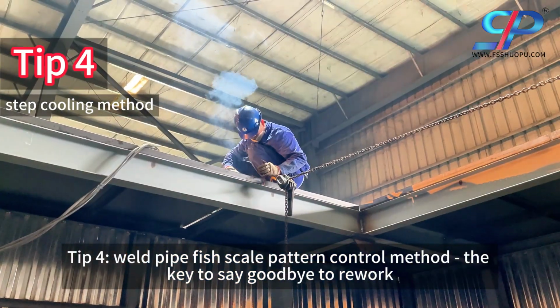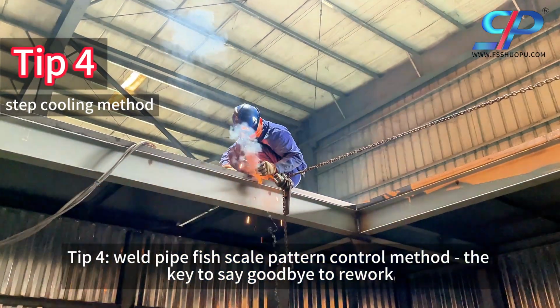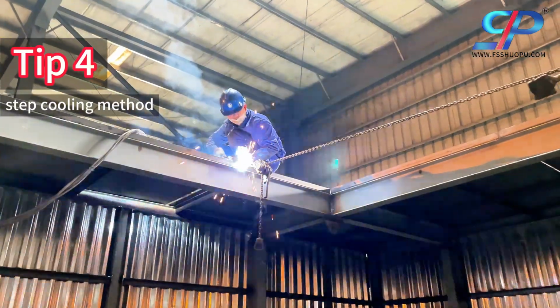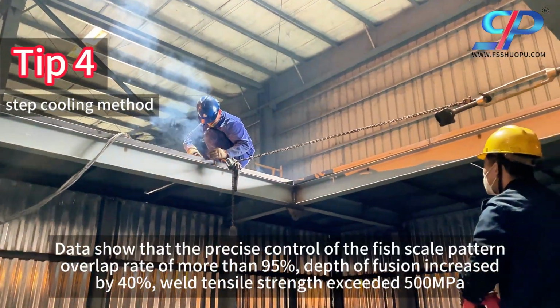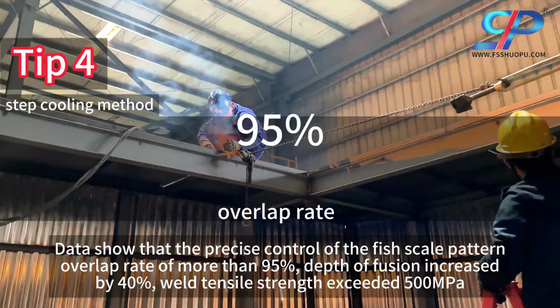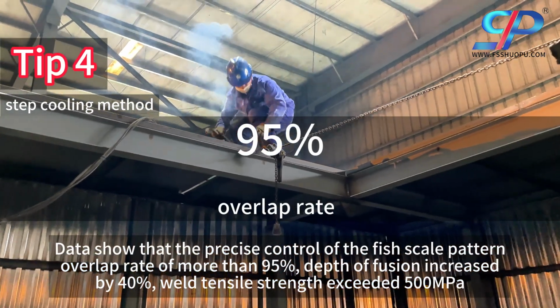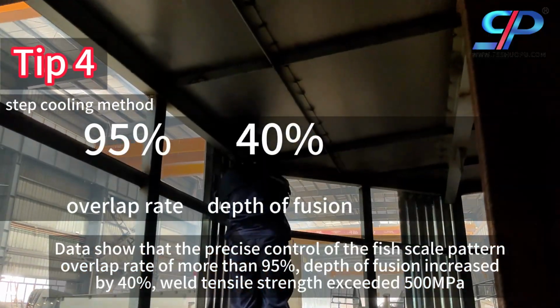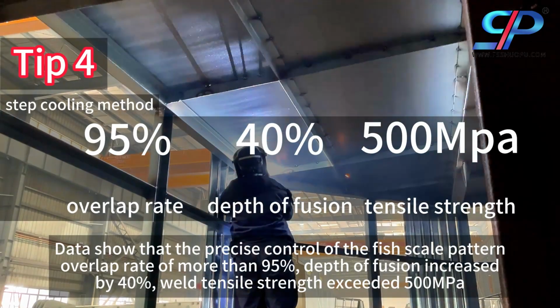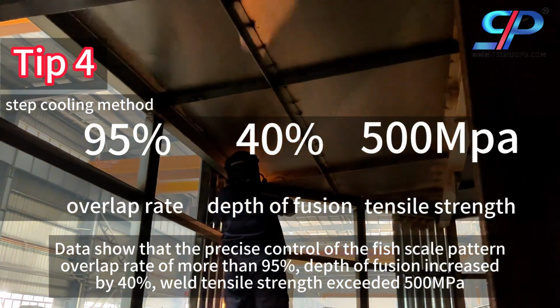Tip 4. Weld pipe fish scale pattern control method, the key to saying goodbye to rework. Data show that with precise control, the fish scale pattern overlap rate is more than 95%, depth of fusion increased by 40%, and weld tensile strength exceeded 500 MPa.